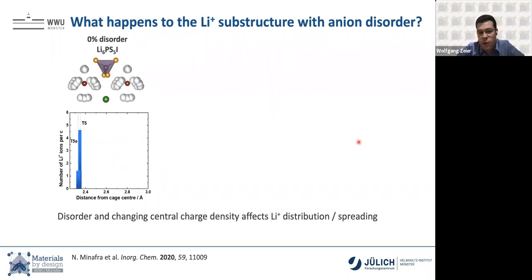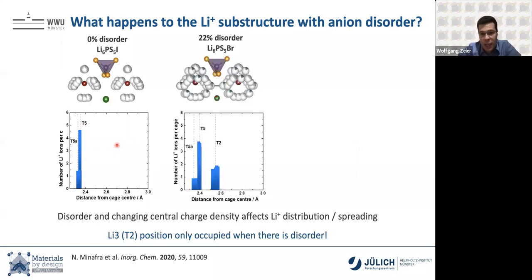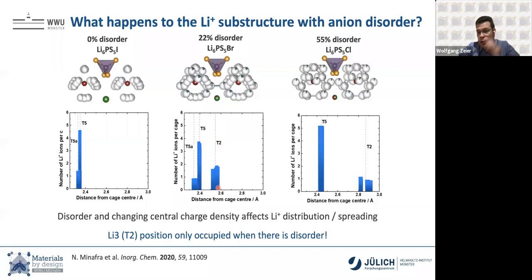So we looked at first the iodide material that has 0% disorder. And here's a function, pretty much a radial distribution, so the number of lithium ions as a function of the distance from the center of the cage. And don't mind the nomenclature that we have here, but in principle, we have these two positions that I talked about earlier. Now, when you go to the bromide, you get that additional position. Mind, this is a material where we have disorder, and there's more lithium further away from the center of the cage. If we go to the chloride, that's even more pronounced, really far out from the center of the cage.